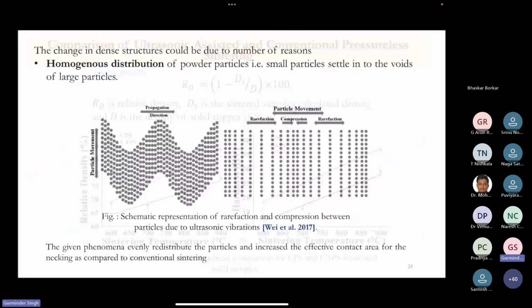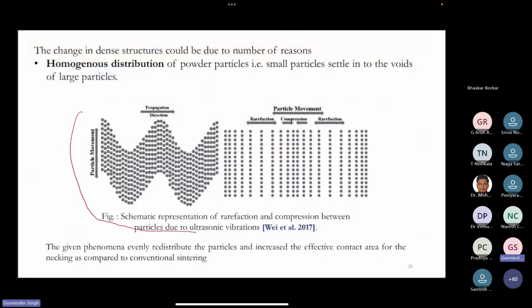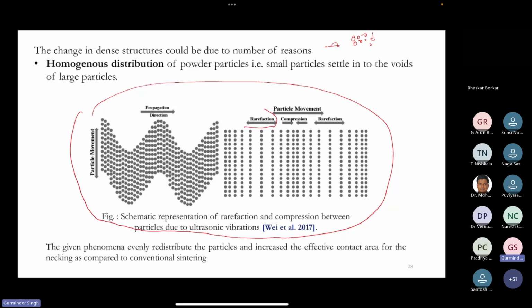So how does this ultrasonic vibration work in the sintering process? First, when you give vibration to any type of powder, it will try to settle down, because you have rarefaction and compression phenomena. It is trying to repel and compress the powders because the vibration is coming in a wave. So it will give time for the small particles to settle into the voids of the large particles.